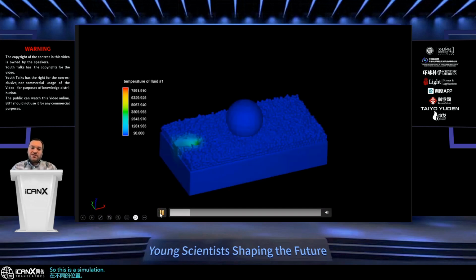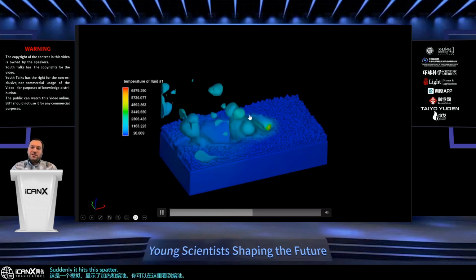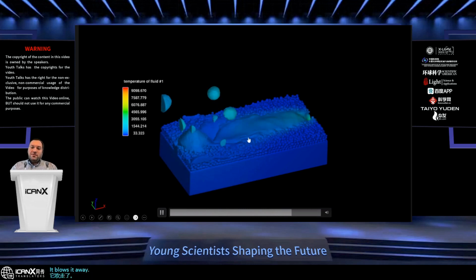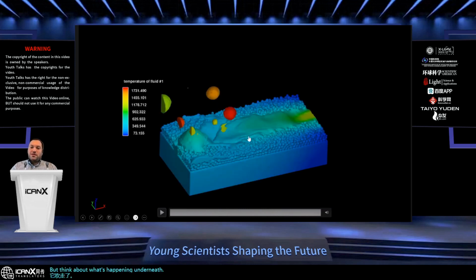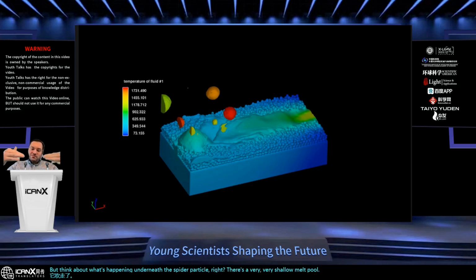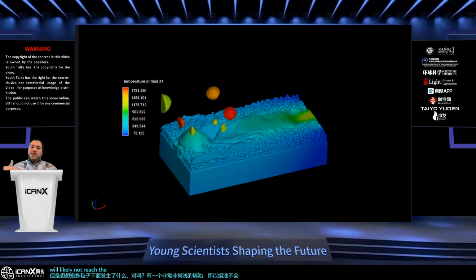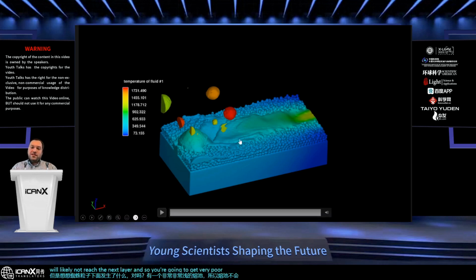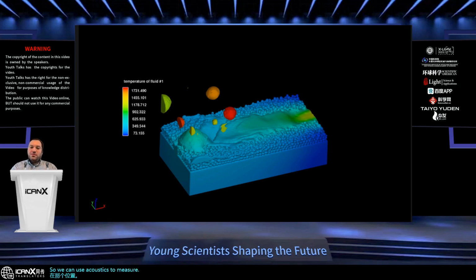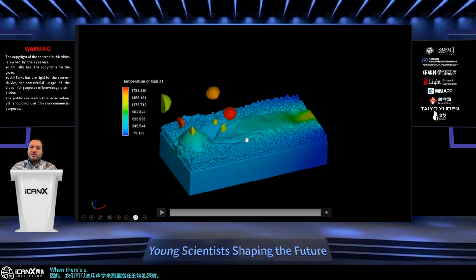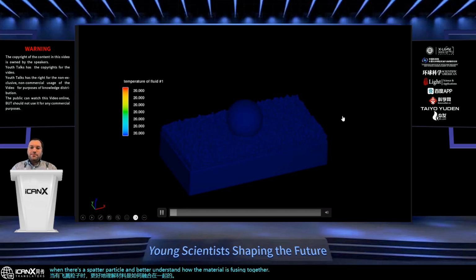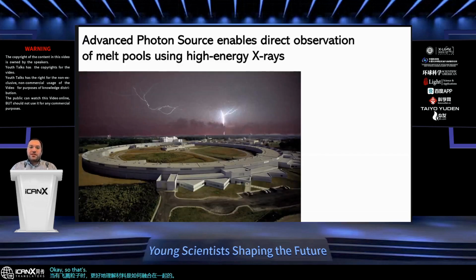This is a simulation that shows the heating and the melt pool. You can see the melt pool here. Suddenly it hits a spatter particle. It blows it away. But think about what's happening underneath the spatter particle, right? There's a very, very shallow melt pool. So the melt pool will likely not reach the next layer. And so you're going to get very poor fusion at that location. So we can use acoustics to measure potentially the melt pool depth when there's a spatter particle, and better understand how the material is fusing together. Okay, so that's a little bit of background.